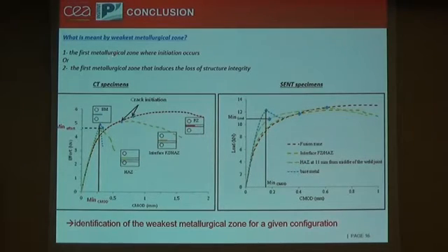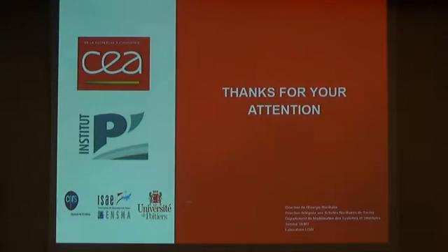In contrast, if we are placed in the second assumption, the heat affected zone will not be a detrimental point, as we have more involvement of plasticity, and it will be just the base metal which represents the weakest metallurgical zone. So finally, this weakest metallurgical zone cannot be identified for all cases, but only for a given configuration. Thanks for your attention.